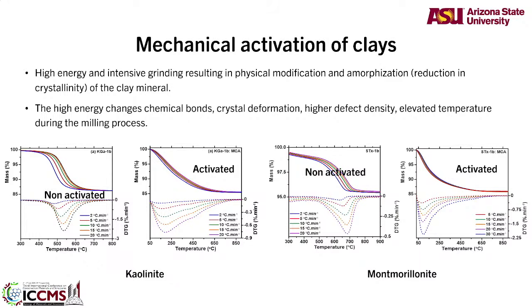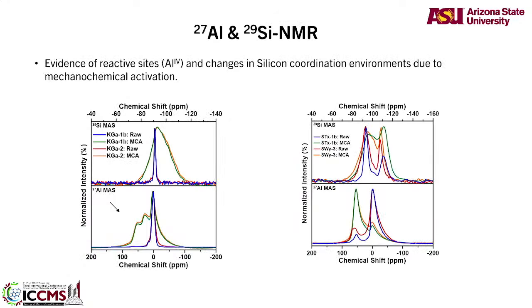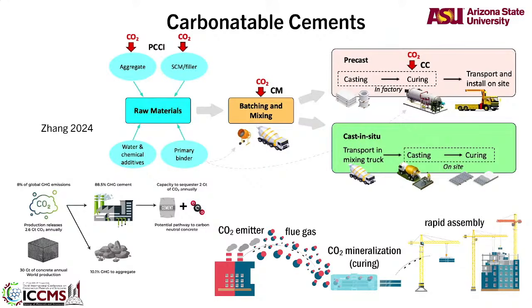So again, simple processing techniques, not simple in the sense that a manufacturer can do it fairly easily, processing techniques to make things better. Again, I'll skip the NMR structure because alumina from 6 coordination, which doesn't do anything, goes to 4 coordination, which is very reactive, 4 oxygen with alumina rather than 6 oxygen with alumina. But what are the other options?